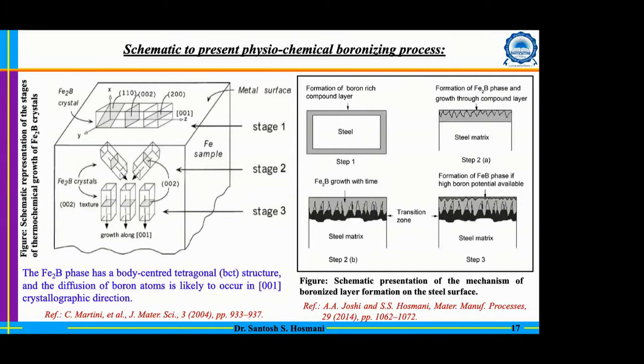Now this particular sawtooth morphology, why is that sawtooth morphology observed? What people propose is that this Fe2B has a tetragonal structure, and boron diffusion generally prefers to migrate, or the boride prefers to grow, along the 001 direction by stacking the planes of 100 as well as 110. So these planes will be stacked in the direction of 001, and because of that, the sawtooth type of morphology is observed in most cases of steel. So that is what is mentioned there.